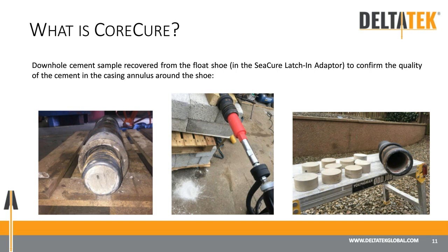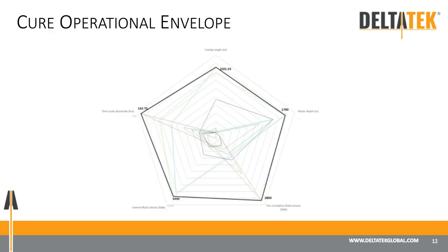DeltaTek's Cure operational envelope is growing. We're at 16 deployments now, 0 NPT attributed to the system, and the envelope has been greatly expanded through substantial deep water deployments in the Eastern Mediterranean, where SeaCure was deployed for 20-inch surface casing strings over a kilometre long in nearly 1,800 metres of water with substantial 3,500 barrel cement jobs. The majority of DeltaTek's Cure deployments are now across conductor strings and somewhat shallower 20-inch surface casing strings, but the envelope is well stretched now, and we're confident that we're able to bring the large majority of deployments within this envelope. However, the system is incredibly robust, as has been shown through the deployments so far.